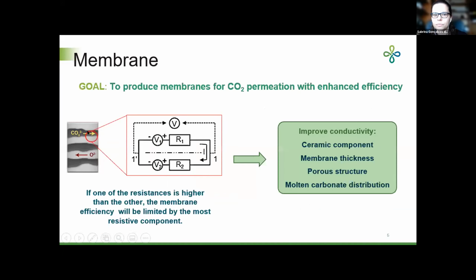So in practice, we can consider that these two phases of the membrane are like parallel cells with ionic resistors and cell thermodynamic voltage associated. This is a simplified electrical circuit here. And since there is no current flowing outside this electrochemical cell, this formal parallel arrangement, in fact, originates a series type association. And for the CO2 to be transported through the ceramic membrane, the flow of carbonate ion needs to be balanced by a counterflow of oxygen ions.